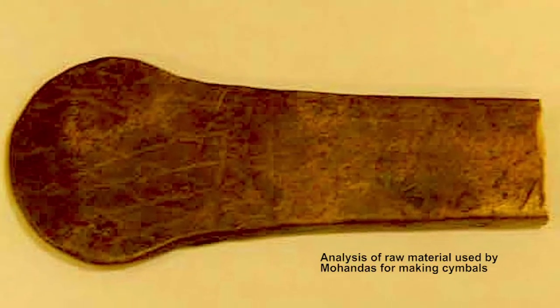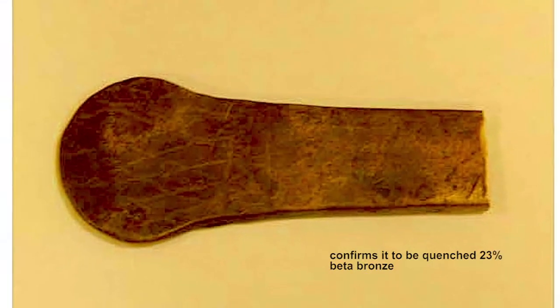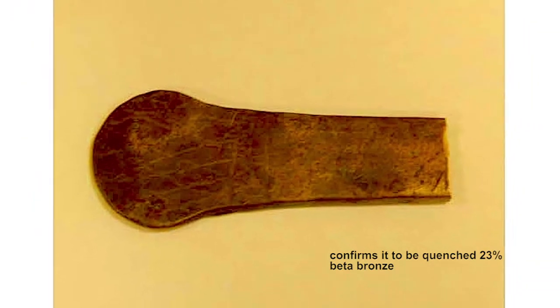The prevalence of the quenched beta phase is what gives the musical tonality for which this alloy was so much sought, and for which so many of those spectacular vessels were melted down, because of the presence of an exact composition of beta bronze of about 23%.